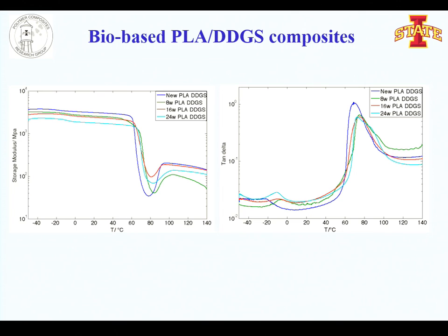There is a very slight decrease in the elastic modulus of the material, and the glass relaxation process of the material also does not change much by adding DDGs or by increasing the degradation time, which indicates that PLA is very hard to degrade in soil.